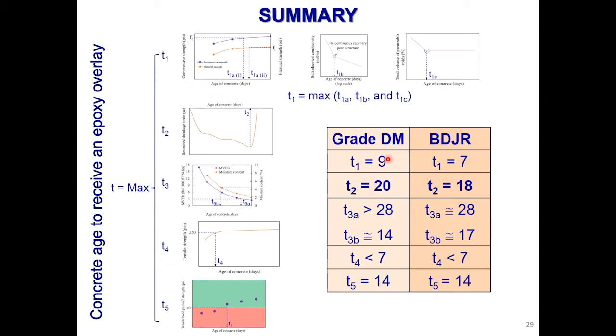Okay. Curing age, yes, it can be like 7 or 9 or 10 days. And then the application age, the cracking age is 20 and 18. Moisture content will stabilize after 14 days in grade DM and 17 days in the mix with type 1. Concrete tensile strength will be gained in less than 7 days in both mixes, so it was not a concern.